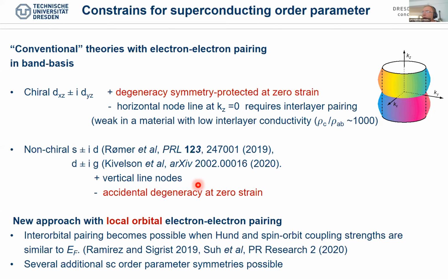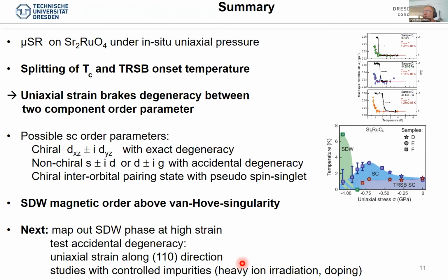There is no way really to understand why they would appear exactly at TC, at the same time. So you form, in the unstrained sample, the time reversal symmetry breaking exactly at TC. There are some new approaches, which look at local orbital electron-electron coupling, by Daniel Achterberg and Carsten Timm and co-workers. From these, there are several additional order parameters possible. So these open up the case that indeed there could be singlet superconductivity by degenerate orbital states in strontium ruthenate.